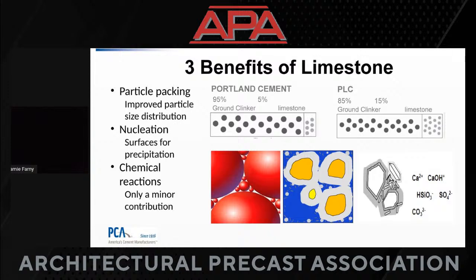Another thing is we have this nucleation effect. So if these orangey or darker yellow particles are cement particles, and then the lighter yellow is a limestone particle, you can see the idea of them being smaller. Well, when we mix cement and water together, the cement starts chemically combining with, reacting with water. It's hydration. And it's not really dissolving, but that cement particle, as it combines, starts creating this cement gel. That's what knits concrete together. That's how it gains strength.